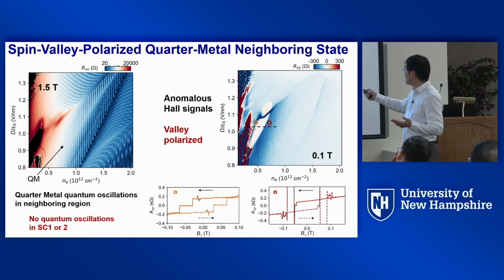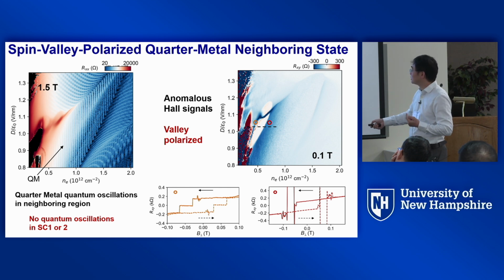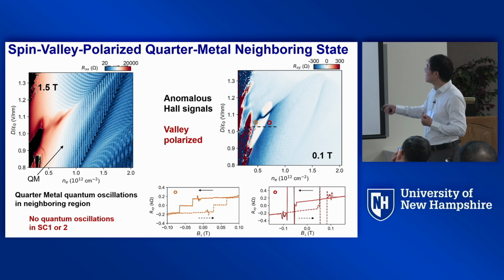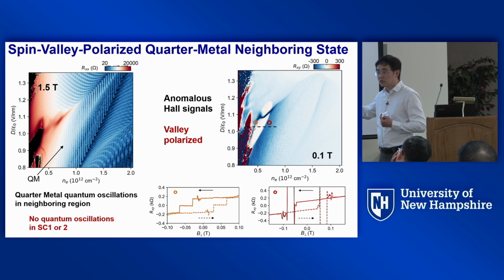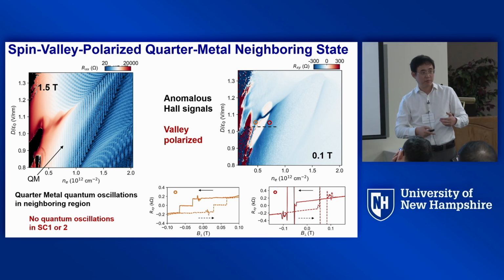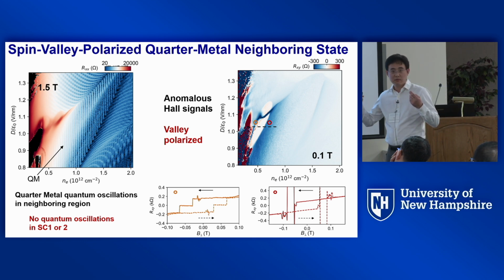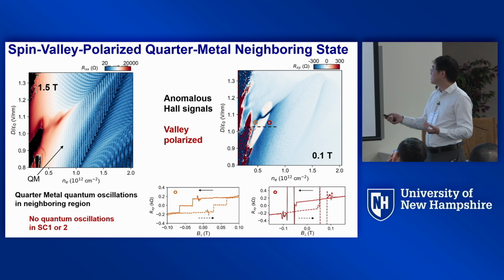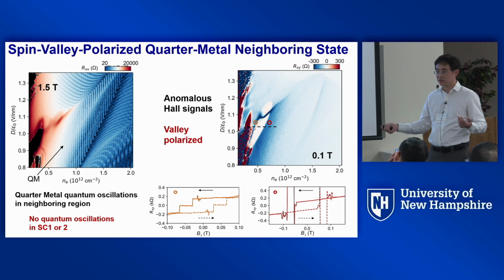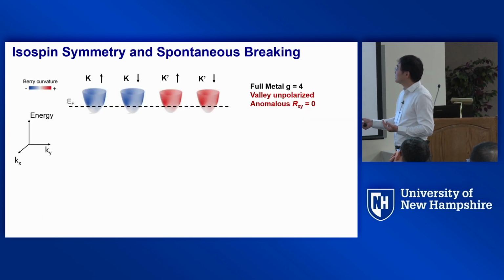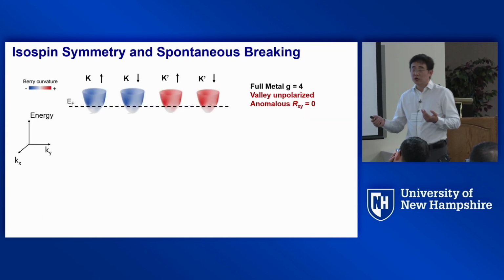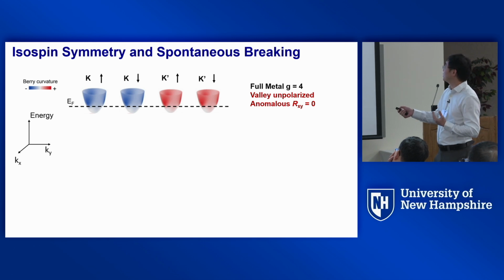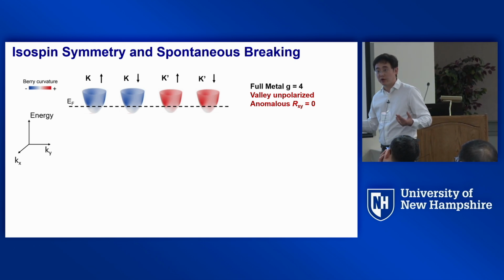And we confirm this is anomalous Hall because when we sweep the out-of-plane magnetic field back and forth, we also get the magnetic hysteresis to the right, which is here, and to the left of SC1. So the superconductivity, at least SC1, seems to be wrapped around by some magnet. And this magnet couples to the out-of-plane field and has hysteresis. So we think this points to a picture related to the so-called isospin symmetry that can be spontaneously broken when you have a flat band.